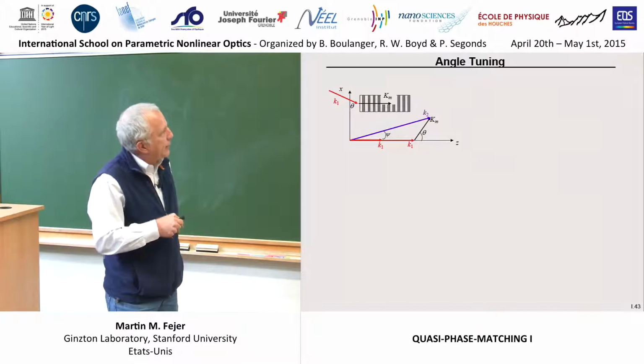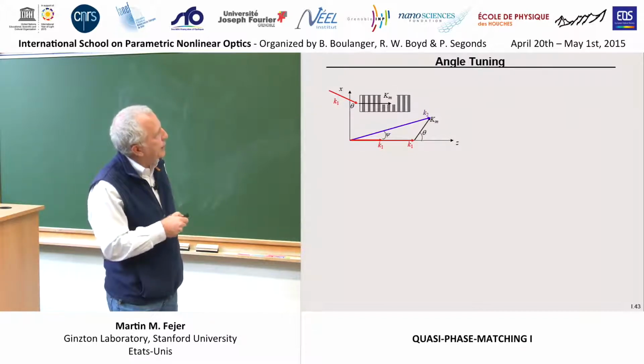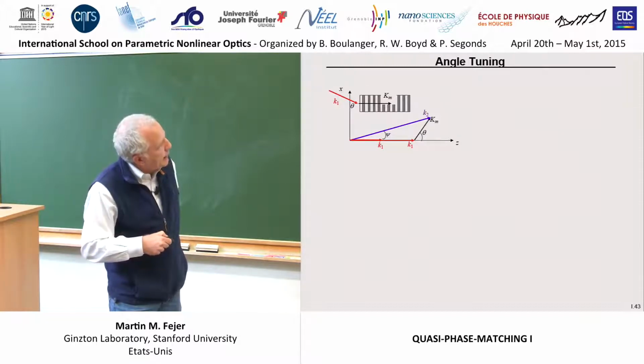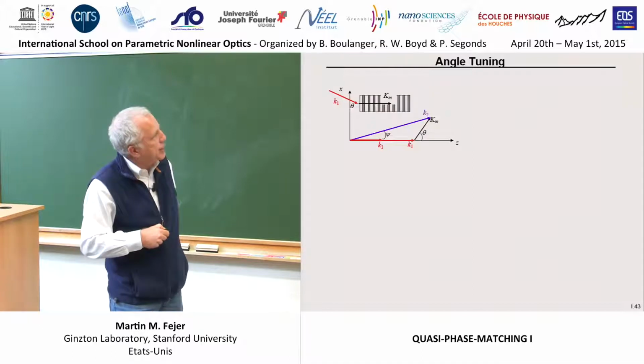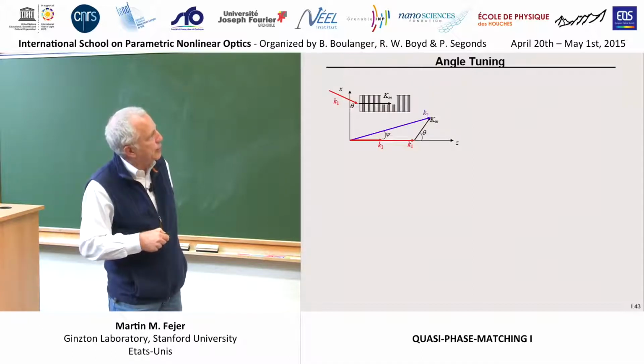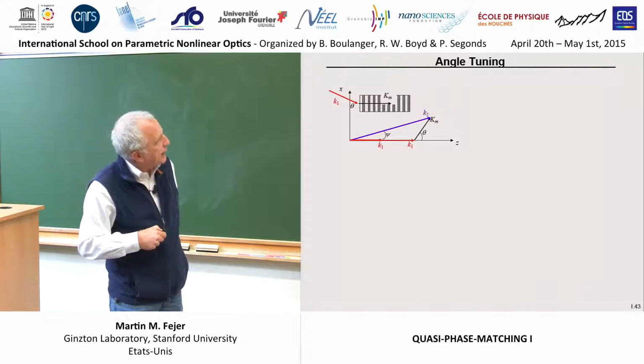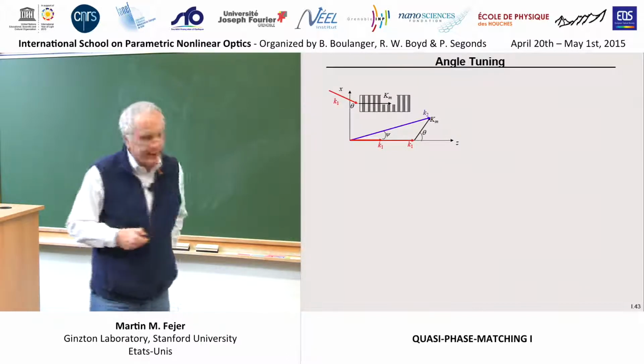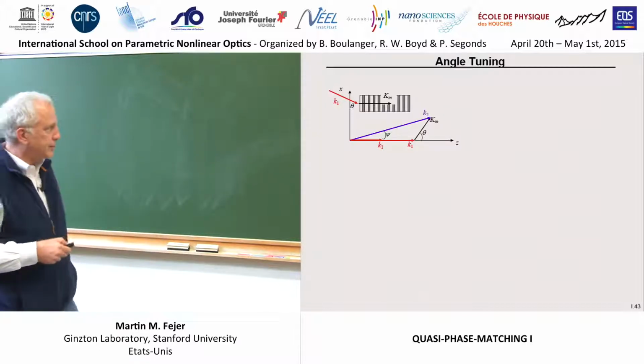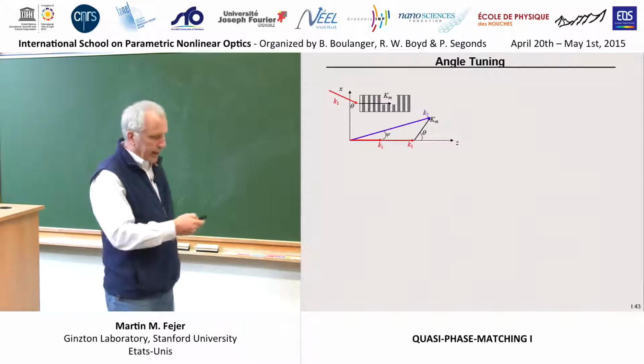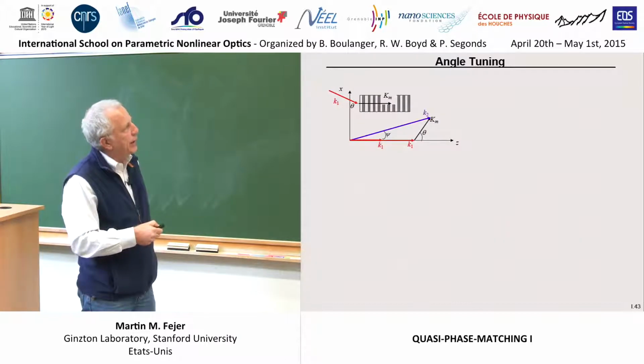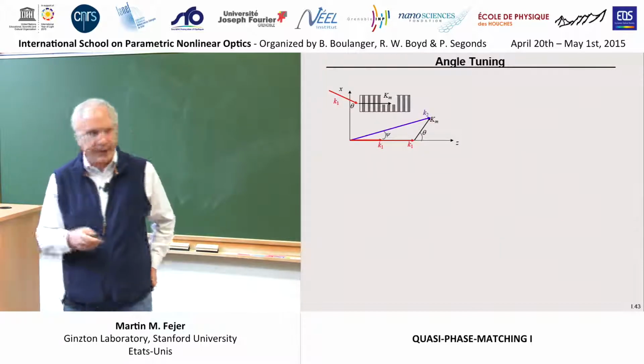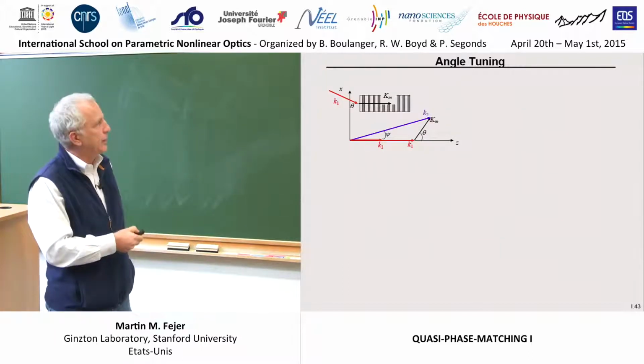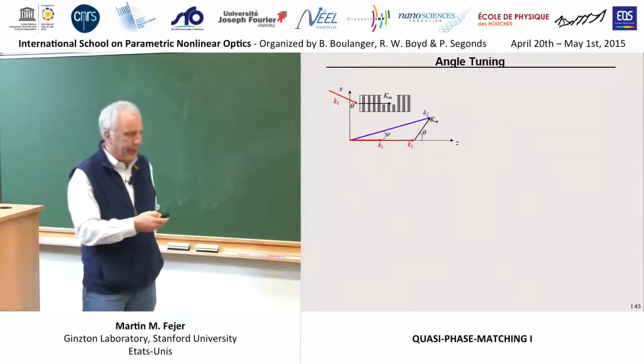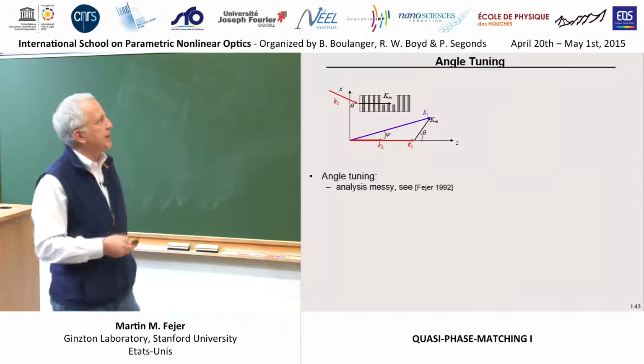If you're coming in at an angle to a quasi-phase matching grating, so the grating K vector is going one way, your pump beam is going a different way, then the nonlinear polarization contains the two fundamental K vectors and the K vector of the grating, and it says that the second harmonic should be generated on the line that closes that triangle. That says that the phase velocity of the harmonic will not be parallel to the phase velocity of the pump or the grating. It's this trigonometric combination. And that's a phase velocity walk-off.